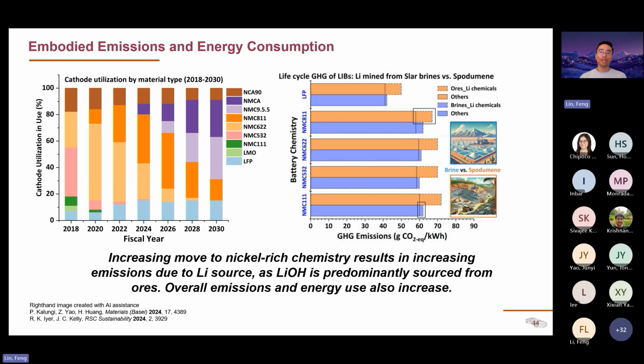made. In order to lithiate the materials in the initial manufacturing, we need a lithiating agent. Basically, you can use lithium hydroxide. You can also use lithium carbonate. Of course, there are other lithium salts people are thinking about, like lithium nitrate. Lithium nitrate is not a typically friendly chemical because after thermal processing it generates nitric oxide. It turns out that lithium hydroxide is preferred for the calcination of NMC materials due to the low melting point and the crystal growth behavior of the NMCs when calcined using lithium hydroxide as precursor.